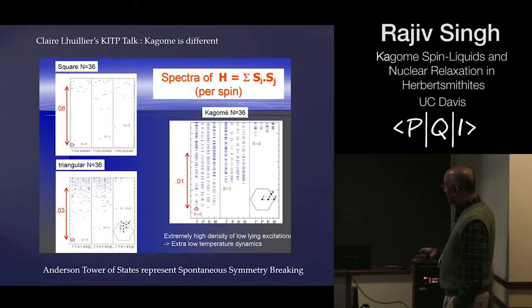And what you find is that this state and this state are far below anything else. And in fact, there is a simple theory of spontaneous symmetry breaking that one can develop, which tells you that it is actually the linear superposition of these states that gives us the null state as a state with spontaneously broken symmetry. And so these states should separate out from everything else and really go to 0 as 1 over n, whereas any other state will only go to 0 as 1 over square root of n. And so that picture is very clear when we look at the spectrum of the square lattice. Actually, something very similar happens for triangular lattice, although it is not as well separated.